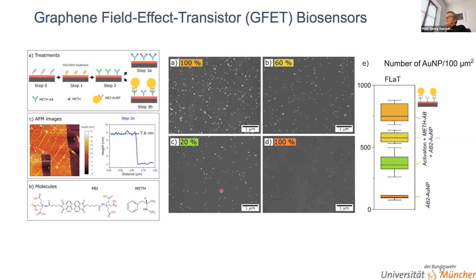This is done by attaching gold particle markers to track how well our functionalization works, and we simply counted those in the SEM. What I wanted to show you is that if you used the wrong antibodies, where the gold particles wouldn't attach, we actually didn't get any functionalization. And here we used different concentrations, and you can see that we can tune the density of our antibodies on our surface.